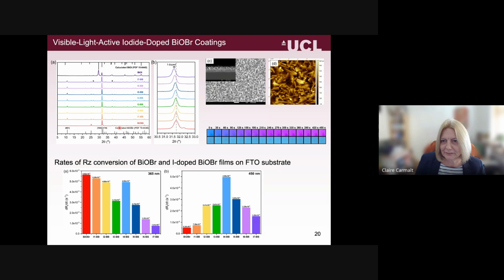So did it work? Well, here's our bismuth oxybromide, and then we've added in dopant amounts of iodine. You can see the XRD, and that's the plain bismuth oxybromide at the top. When you look at the XRD, you can see the peak shifting as we're doping with iodine. And then this is the SEM and the AFM, so you can see the sort of morphology you'd expect for these oxyhalides. This picture shows you the digital images. So this is an uncoated substrate, and as expected, you see no change. This is one of our films, and you can see the change as it's progressing, as the photocatalysis is working.